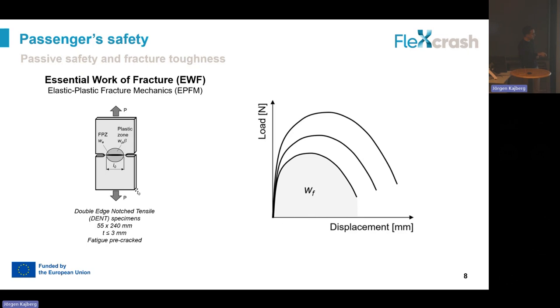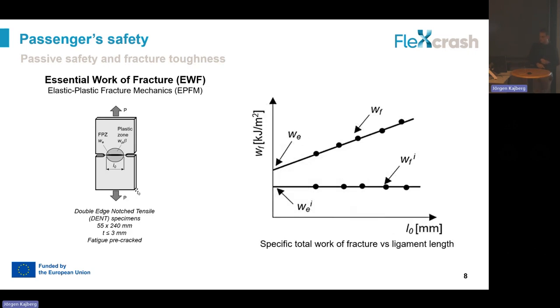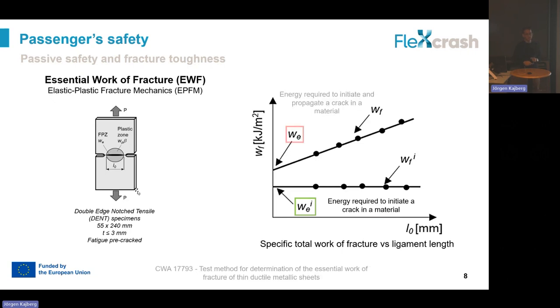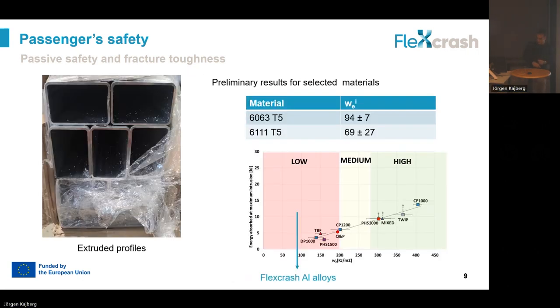So here mainly we have the different ligament length. We are testing them, and here you can see the load displacement curves, and we are measuring the energy below the curve. So if we measure this energy for each specimen, then we can calculate the energy required to initiate the crack in the material, but also to propagate it.